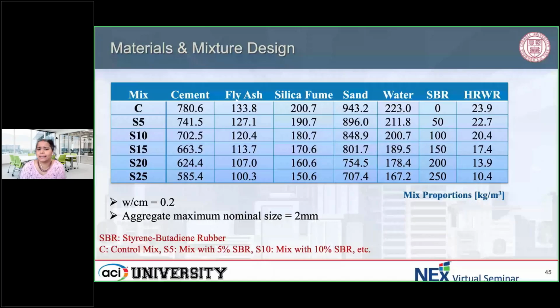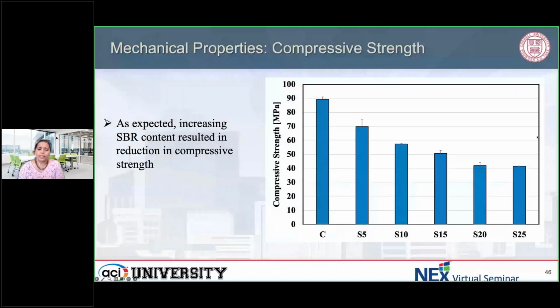So we design these different mixtures, and then you can see that the high range water reducer components are changing. This is because you want to achieve a certain flowability. So when you achieve a certain flowability, you can see how as you're increasing the amount of SBR inside your mixture, of course, our compressive strength is going down. But as expected, the interesting thing is that your flexural strength doesn't increase at the same rate.